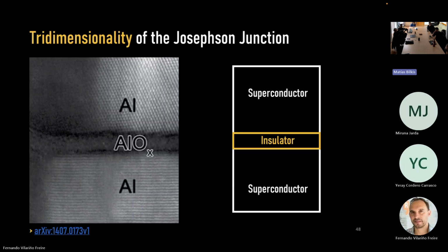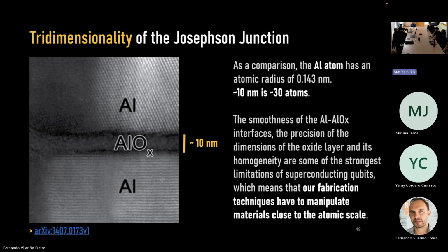An additional headache is that the Josephson junction is three-dimensional. It's a 3D structure. It's not only planar, which means that usually, as we do it, we put an aluminum layer, an aluminum oxide layer, and another aluminum layer. And roughly this insulator is around 10 nanometers. Then you can go to Wikipedia, look at how big an aluminum atom is, and I made a quick calculation, and it will fit around 30 atoms, something like that. And this is a problem because the smoothness of the interface between aluminum and aluminum oxide, also the homogeneity, the impurities, the defects, is a limit in the quality of superconducting qubits. So you really have to go very close to the atomic scale in the manipulation of your hardware to be able to make good quality qubits.